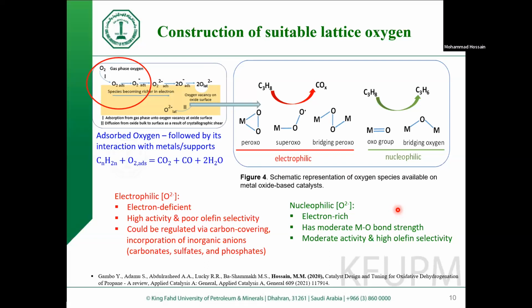Now, in addition to mechanism, the type of oxygen that is going to interact with the hydrocarbon is also very important in order to achieve the selective product. When the oxygen interacts with metal, first it will adsorb on the surface, and then gradually it will interact with the active species and become lattice oxygen. So this way we can have three types of oxygen. One is the adsorbed phase of oxygen, which is very reactive but not selective. They interact with the hydrocarbon, both alkane and alkenes, to produce complete combustion products, CO and CO2.